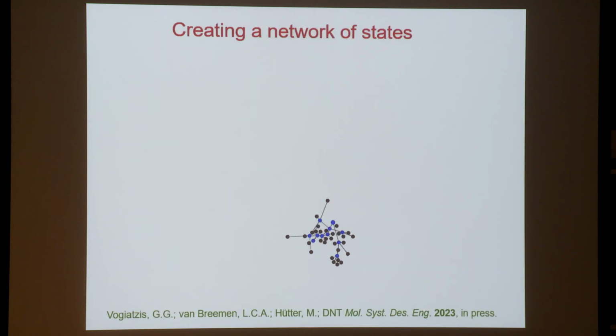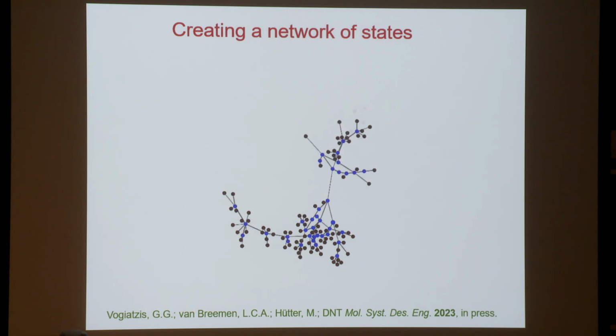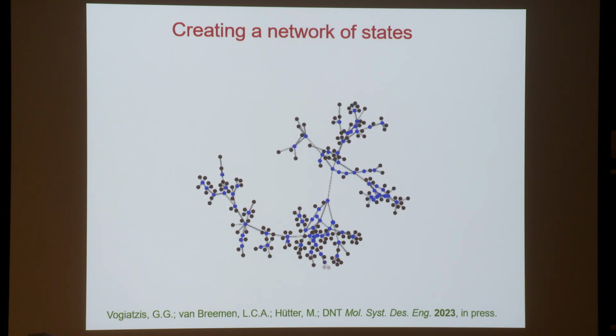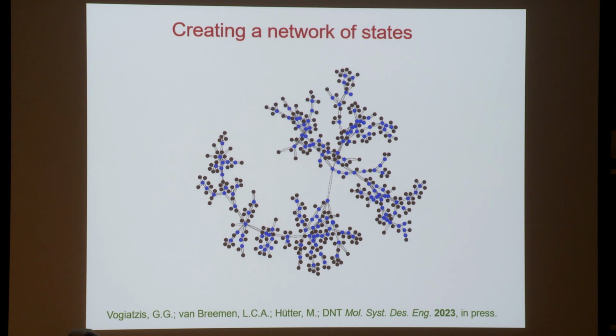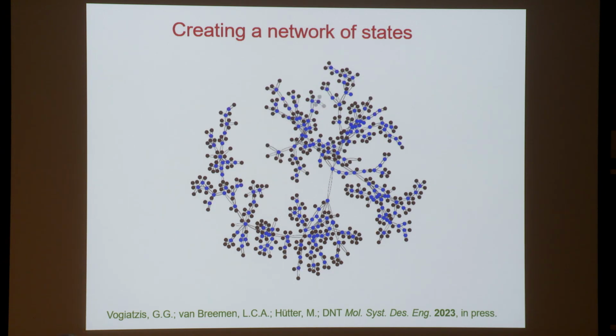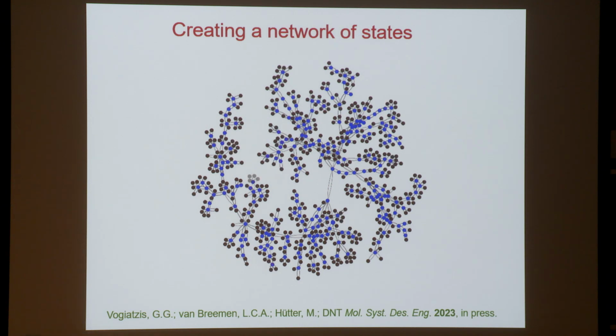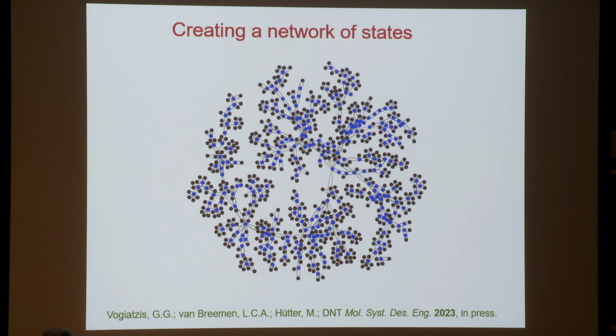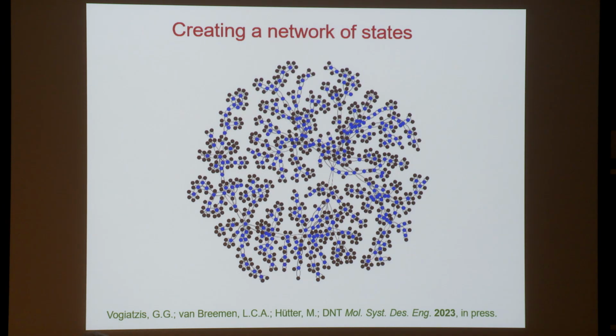One can start from a minimum and sample many other minima connected to it. And in the graph that results, I distinguish between what we call explored states, shown in blue. These are states for which we have calculated as many paths as possible leading out of them. And boundary states, the black ones, are states which are connected to explored states, but not yet explored themselves. In the beginning, one starts with a small set of explored states. As time goes by, one has to augment this set. So one takes one of the boundary states according to the fluxes leading into them and explores it, which means that it joins the rest of the explored states and its neighbors become boundary states.